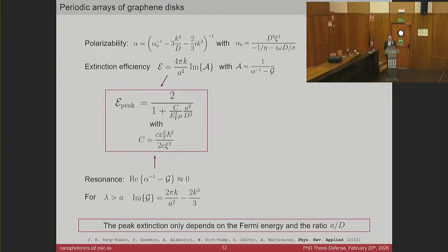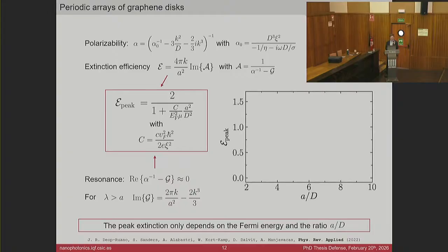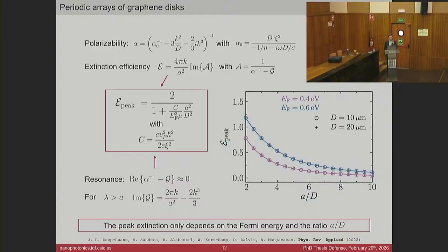With all of these ingredients, we can obtain an analytical expression for the peak extinction efficiency that, as we see here, only depends on the ratio of the period to the diameter, as we suspected. If we compare it to some numerical results that I showed to you before for 10 microns and 20 microns diameter, and compare it with this analytical expression that I plot with this solid curve, we can see that there is a really good match. And the same for the rest of the cases that I analyzed.